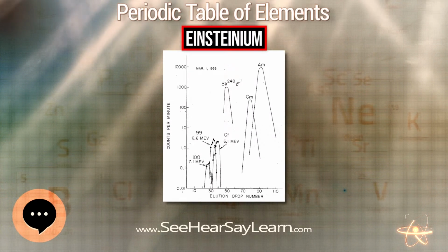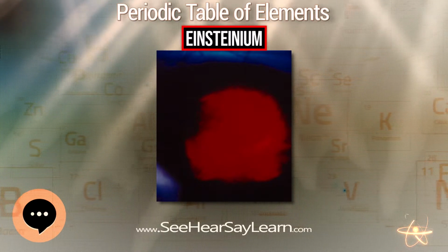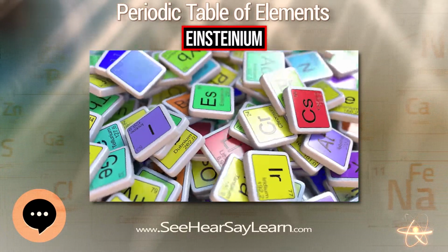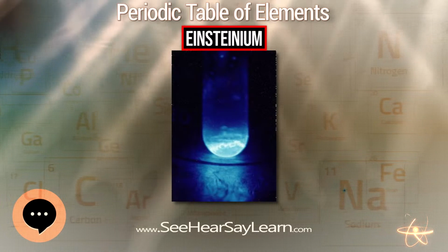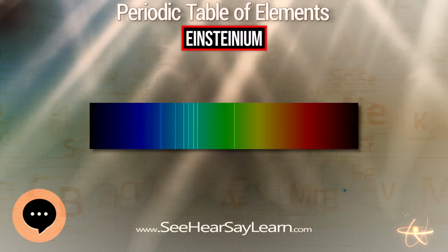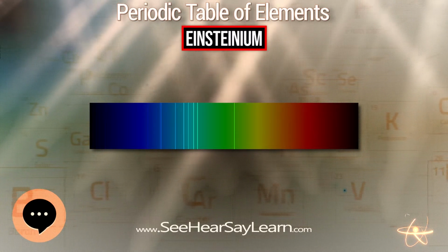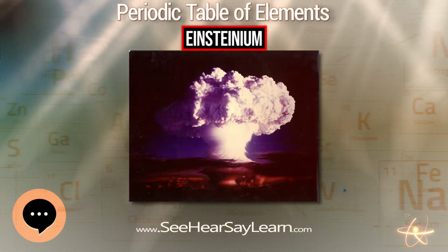Einsteinium is highly reactive and therefore strong reducing agents are required to obtain the pure metal from its compounds. This can be achieved by reduction of Einsteinium fluoride with metallic lithium. However, owing to its low melting point and high rate of self-radiation damage, Einsteinium has high vapor pressure, which is higher than that of lithium fluoride. This makes this reduction reaction rather inefficient.